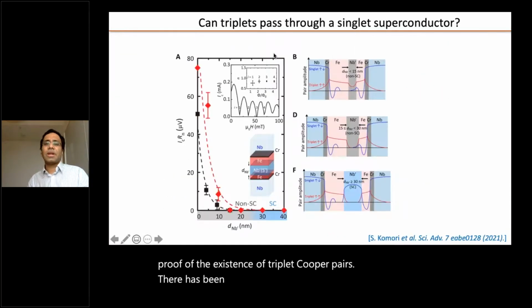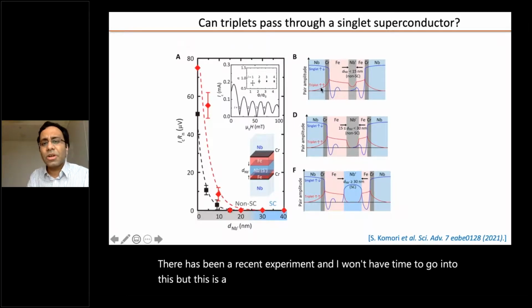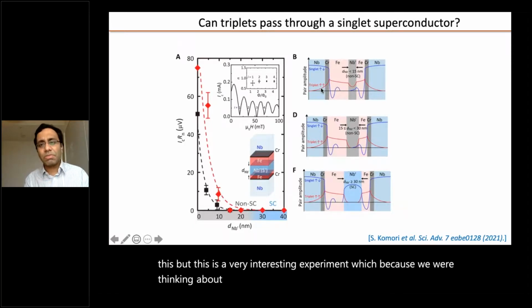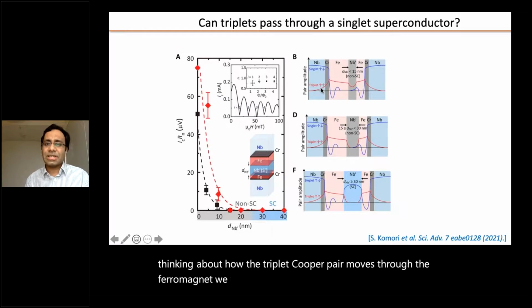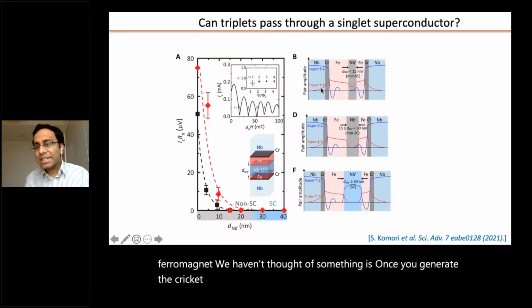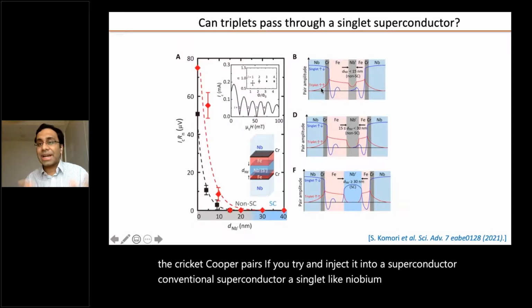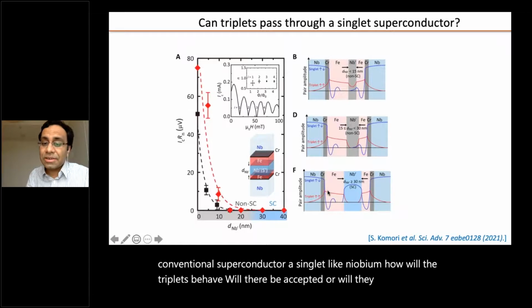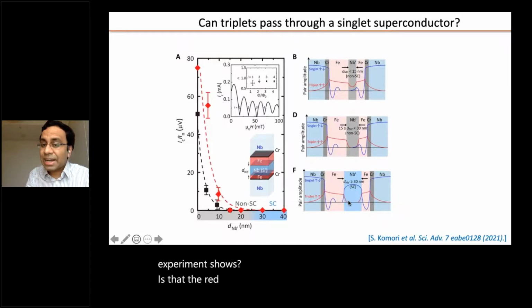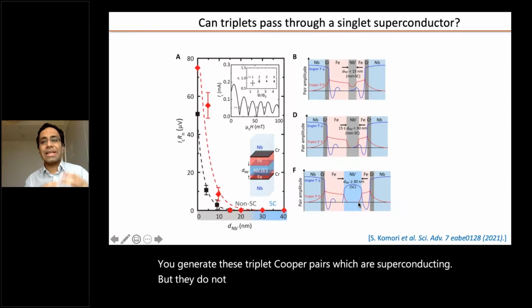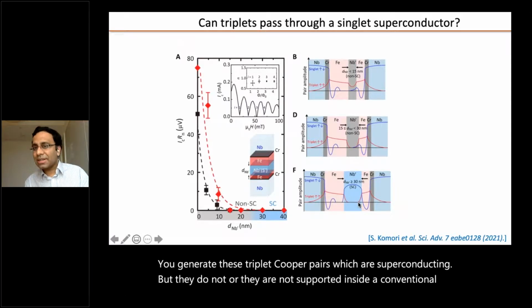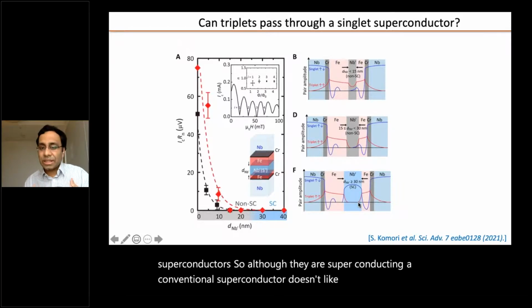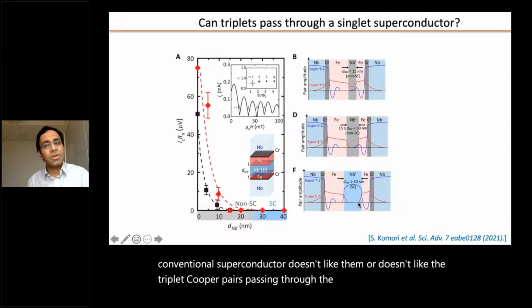There has been a recent experiment, and I won't have time to go into this, but it is a very interesting experiment, because we were thinking about how the triplet Cooper pair moves through the ferromagnet, but we haven't thought about what happens once you generate the triplet Cooper pairs and try to inject them into a conventional, singlet superconductor like niobium. How will the triplets behave? Will they be accepted or will they be rejected? What this experiment shows is that the red line, showing the density of the triplet pairs, dies down inside a conventional superconductor. So this is very surprising. You generate these triplet Cooper pairs, which are superconducting, but they are not supported inside a conventional superconductor. So although they are superconducting, a conventional superconductor doesn't like the triplet Cooper pairs passing through it. So it's a very strange form of superconductivity.